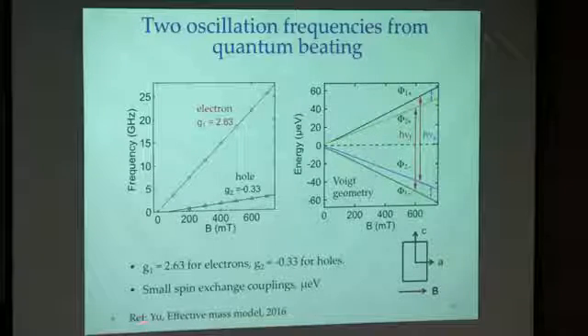By collaboration with a theorist, he calculated the g factors for electrons and holes. Based on his calculation, we realized this number is very close to the calculation for electrons, and that number is close to the calculation for holes, with a minus sign there. Our measurements do not really tell the sign of the g factor, but based on his calculation, this is likely to have a negative sign. That's for electrons, and this is for holes.